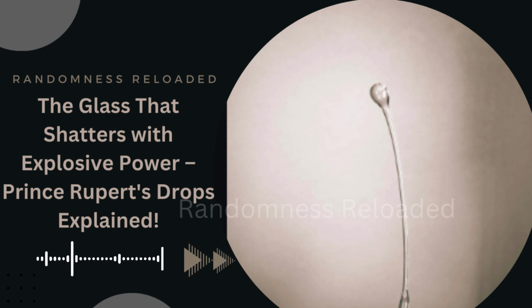Adding those bubbles totally messed up the formation of the Prince Rupert drops. They couldn't even hold their shape. It's like the bubbles worked against the forces that usually make the drops so strong. Right. It's counterintuitive. So how did the researchers explain that? Well, they concluded that those pre-existing bubbles messed with the balance of stresses during cooling. So instead of a smooth, evenly compressed outer layer, you end up with weak points where the bubbles were. Oh, like little ticking time bombs, just waiting to go off. Pretty much. It shows just how sensitive the whole process is. Even tiny disruptions can totally change the outcome.